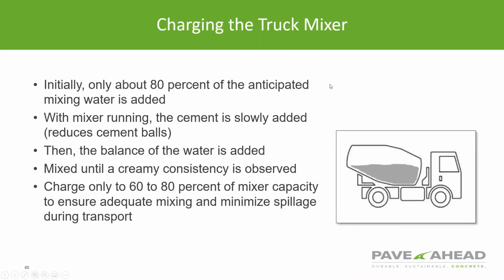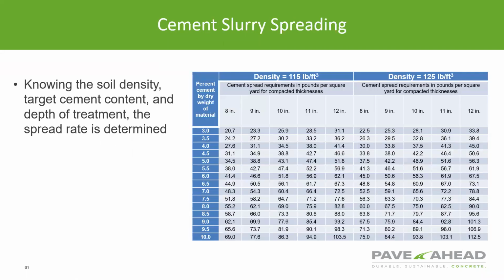As far as charging the mixer, initially, about 80% of the water is added. With the mixer running, the cement is added slowly, then the balance of the water. And generally, you charge only 60 to 80% of the mixer capacity to ensure adequate mixing and minimizing spillage during transport. So you can't utilize the capacities that you would with normal concrete.